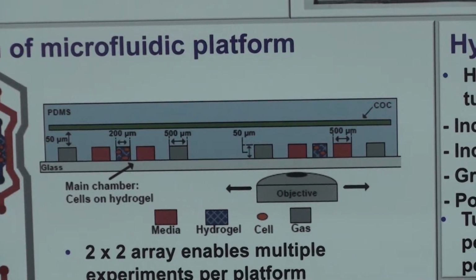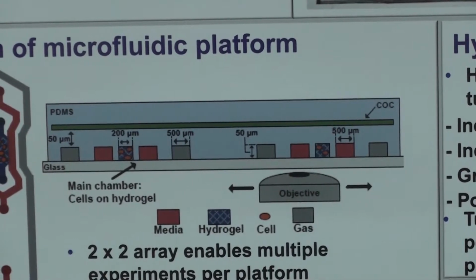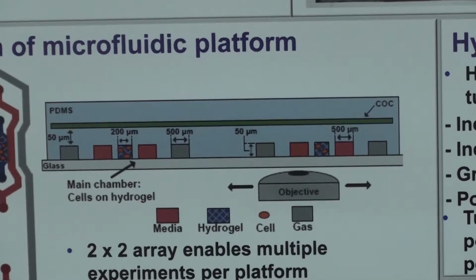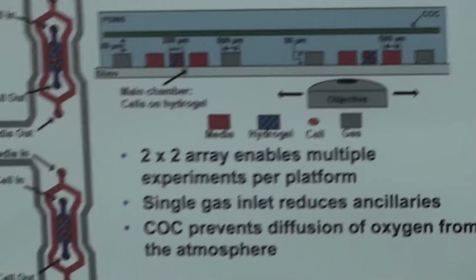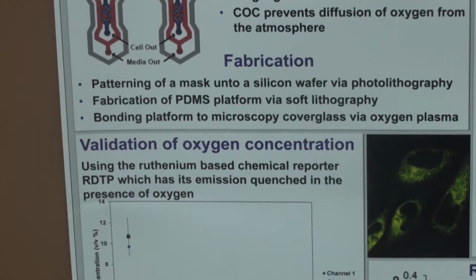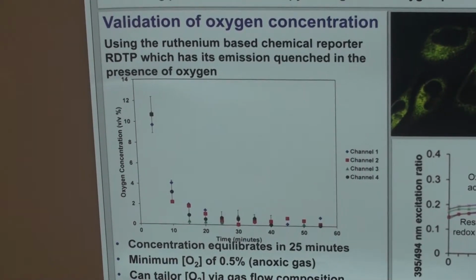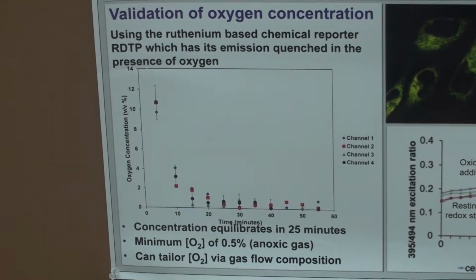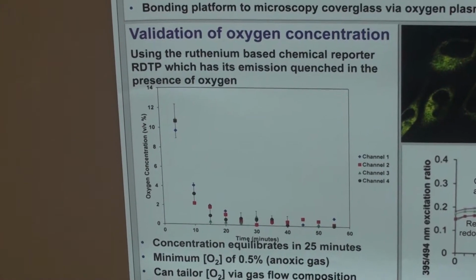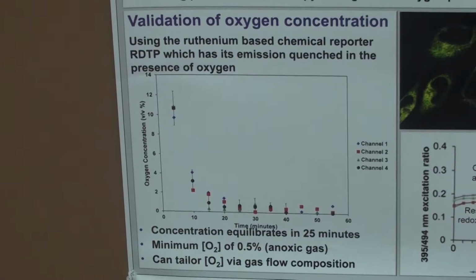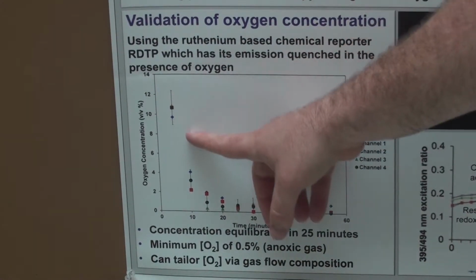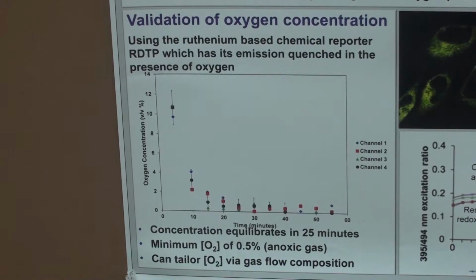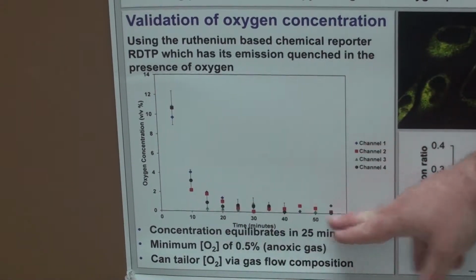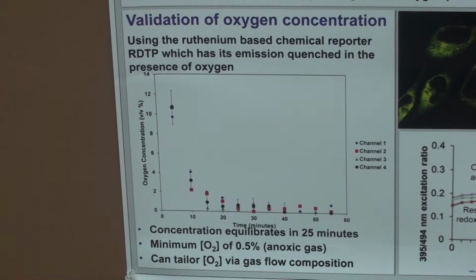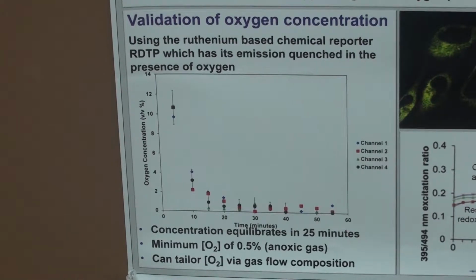We first validated this device in COMSOL for oxygen diffusion, and then we used the ruthenium-based chemical reporter RDTP, which has a fluorescent emission that is quenched in the presence of oxygen. So we loaded it into the main area of the device, started imaging it, and it wasn't fluorescent at all. As our oxygen concentration dropped, its fluorescence increased and increased until it hit a steady state at around 12 minutes at 0.5% oxygen by volume, proving that we have a hypoxic cell culture platform.